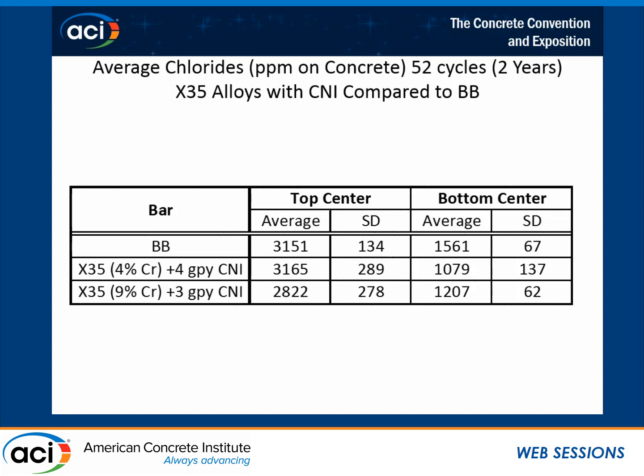In the case of these, the bottom bars were not corroding, but the black steel at somewhere around 48 cycles or so actually started corroding in the bottom bar. And mind you, these are big differences, long distance and everything. So that's something to worry about with cracks. It's not just the top bar, it could be the bottom bars.